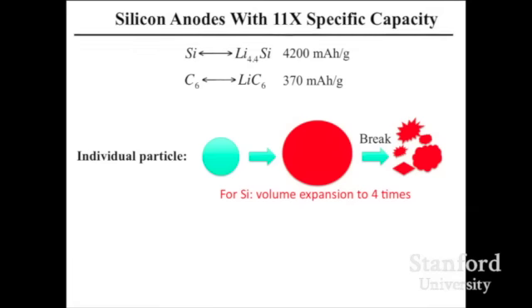But silicon has a problem, from the atomic bonding scale to the particle to the big electrode scale. Lithium comes in, breaks all the silicon-silicon bonding, and we form lithium-silicon bonding. The volume expands very big, 400%, and then a lot of stress builds up, and they break. This breaking is really killing the battery. The first time you charge your battery, the battery has already died.